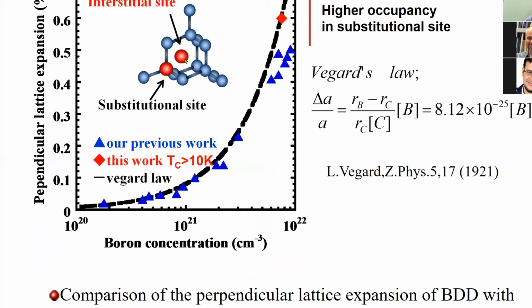Diamond has a structure with very large regions for the interstitial site, so the impurity is easily incorporated also in the interstitial site. If we prohibit that and more efficiently introduce the boron, then only the substitution site is used. This is what we get in some conditions where we get high TC. So very simply we can explain how we get high TC, how we get substitutional site boron. This is a very simple idea, but it works.